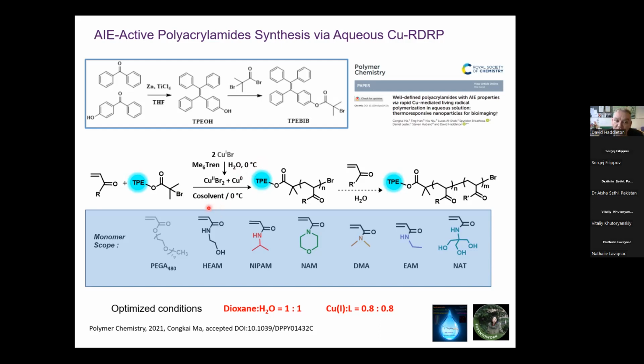We can use co-solvents. In this particular case, our initiator is not soluble in water, so we'll dissolve that in a co-solvent that is miscible with water, and we add the solution of the water-miscible solvent with the initiator into the solution of disproportionated copper in water, and you can polymerize, well, any acrylamide you want. We'll polymerize in a few minutes, really, and the dispersity you get again is less than 1.1.